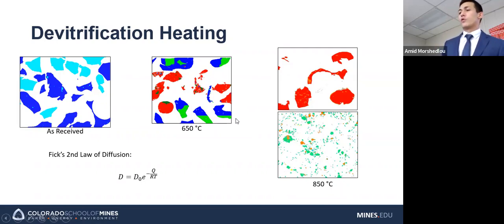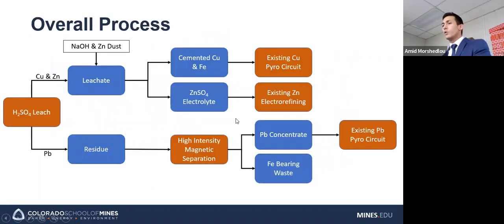So because of this, we sort of ruled out mineral processing methods and pre-concentration and decided to go straight into leaching. And so we've come up with a general process to do this, and it starts with sulfuric acid leach. From there, we get two products, a leachate and a residue. The copper and zinc form sulfates, which are soluble, and those report to the leachate. The lead also forms a sulfate, but lead sulfate is not soluble, so it remains in the residue.